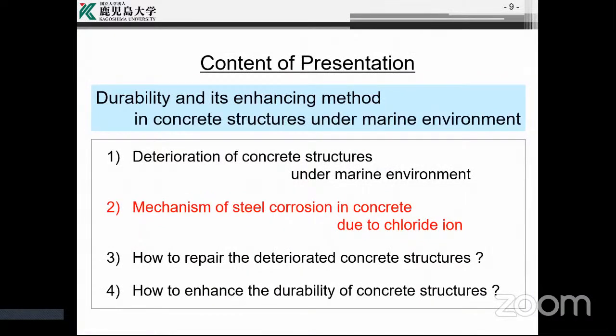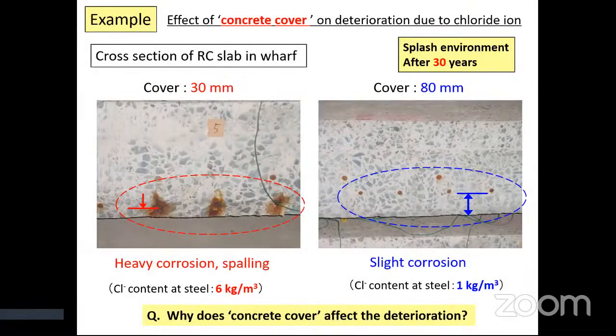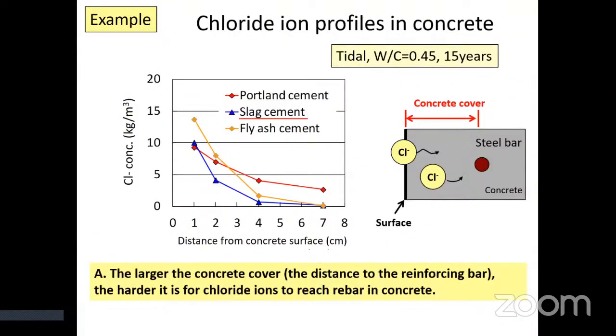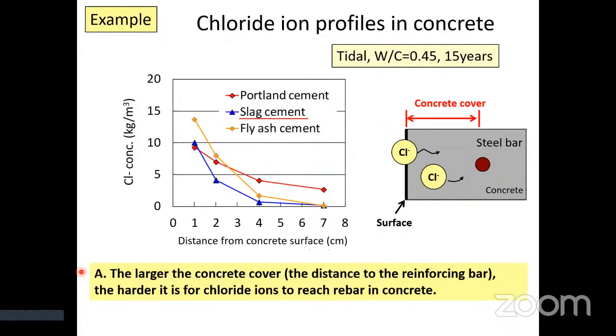From now, I'll explain mechanism of steel corrosion in concrete due to chloride ion. Before explaining corrosion mechanism, I'll introduce an easy example. This picture is an example of the clear effect of concrete cover on deterioration due to chloride ion. This is a cross section of RC slab in wharf after 30 years in the same splash environment. In the case of 30 mm cover, severe corrosion was observed. On the other hand, in the case of 80 mm cover, only slight corrosion was observed. Why? The answer is, the larger the concrete cover, the harder it is for chloride ions to reach rebar in concrete.